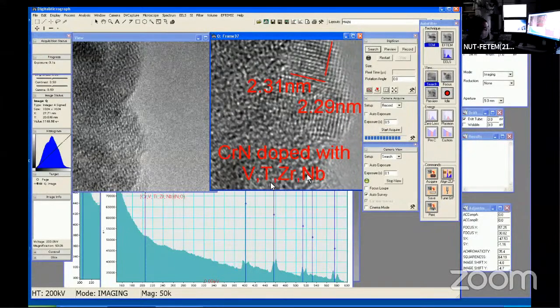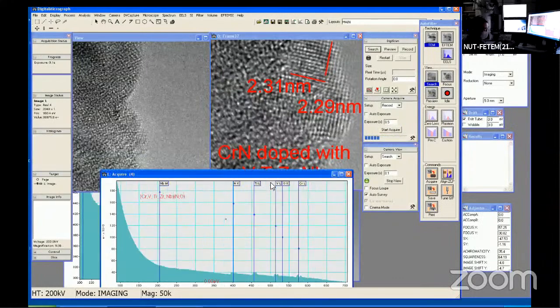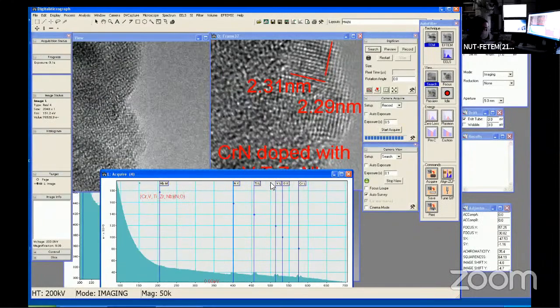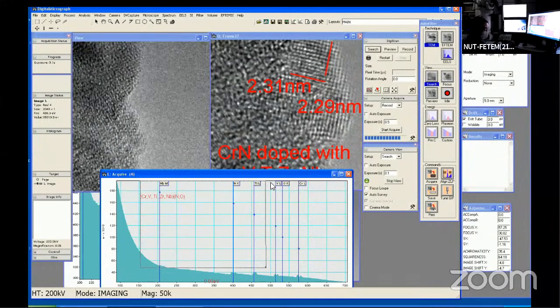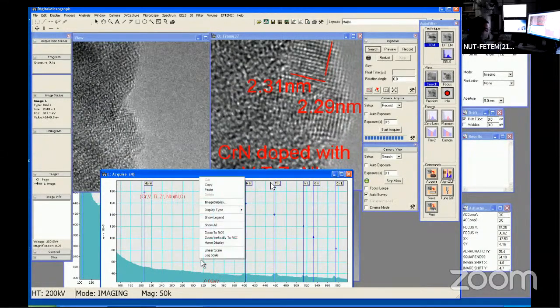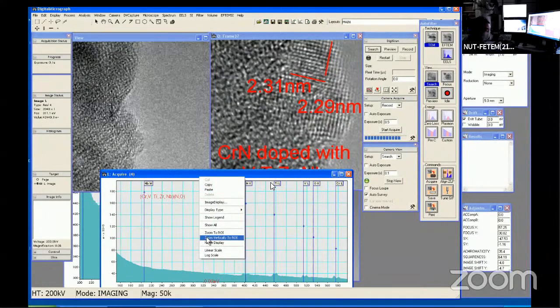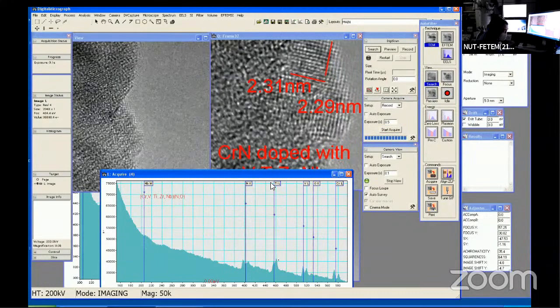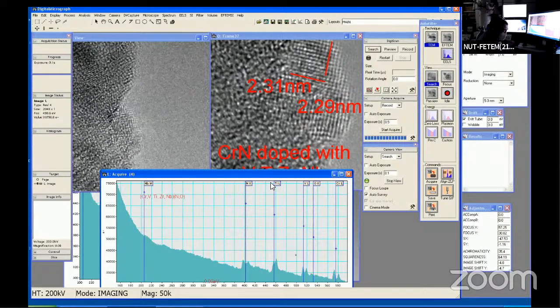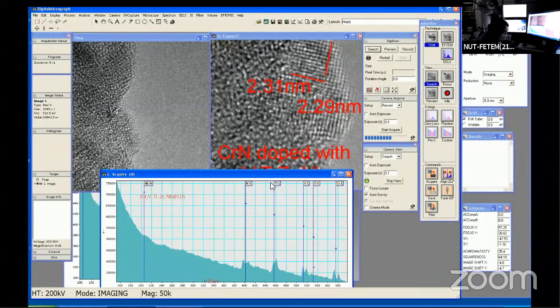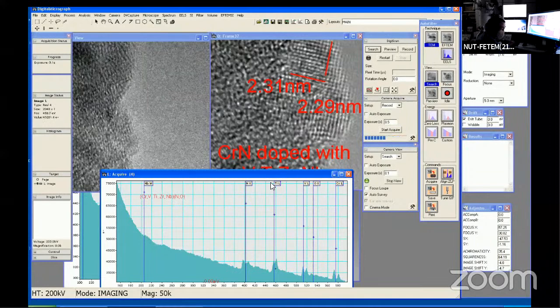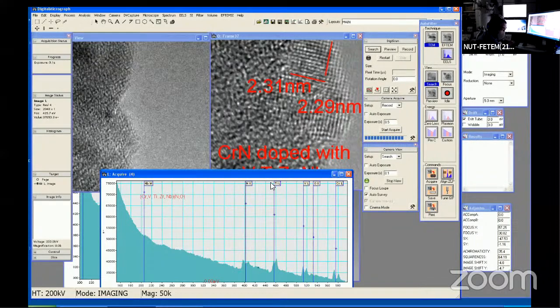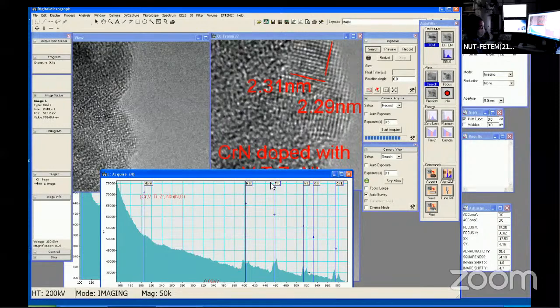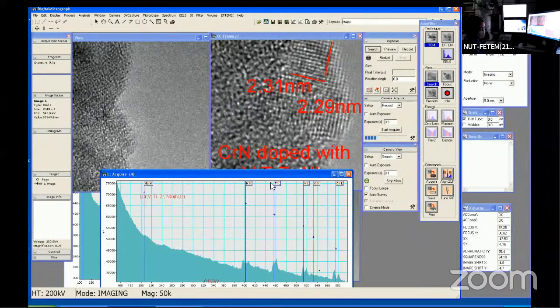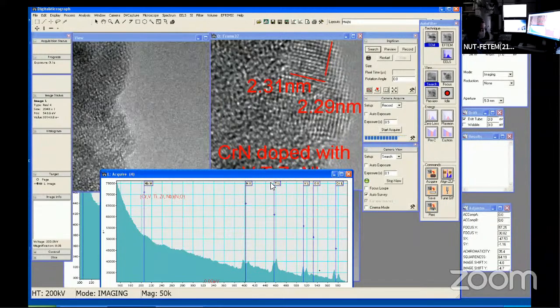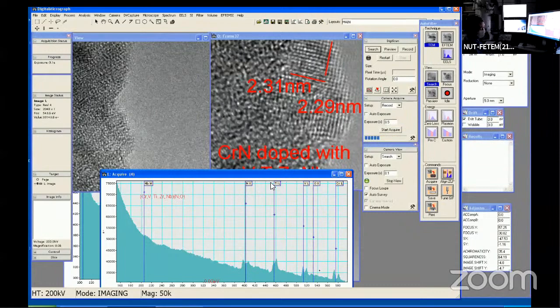But we are not sure about oxygen and nitrogen. And so what I did was an EELS analysis, and this is the EELS spectrum. When we zoom in on the EELS spectrum, you may see heavy elements, titanium and vanadium and chromium, along with the oxygen small peak and the nitrogen edges. So it means we intend to make a nitride, but a small amount of oxygen is also involved. Actually what we found was that oxygen doping can enhance the hardness by 60%. So it is favorable for the hardness increase of this material.